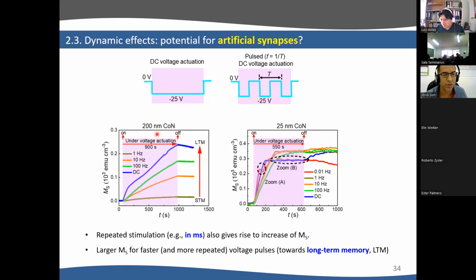Let's focus first on the 200 nanometers. What you can see here is that if you go very slow, like 1 hertz, the magnetization almost does not increase. And if you go very fast, 100 hertz, it increases much faster. This is analogous to what happens with the brain. Because imagine during this almost 1000 seconds, at 100 hertz, you will have a lot of stimulus, right? It's the same as when we see an image or something, and we see it many, many times, it is retained better in the brain, right?